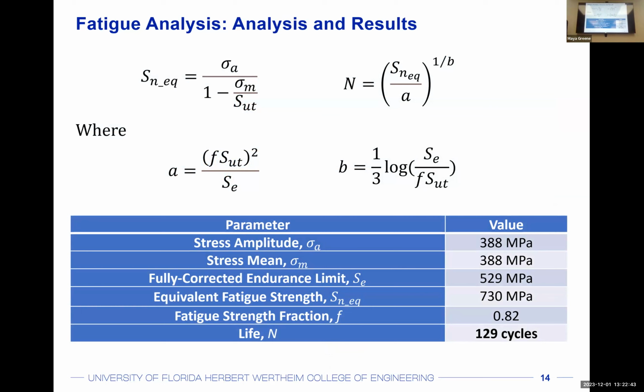The cycles to failure was then calculated using this calculated equivalent fatigue strength as well as the other parameters discussed. This resulted in a life of 129 cycles. Again, given the variability of the dust on the moon, we were aiming for a cycles to failure somewhere around this range, in the low hundreds, for very massive boulders that you wouldn't expect the PSI to even kick up.